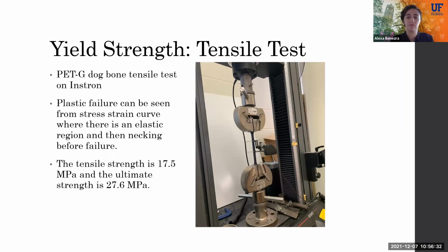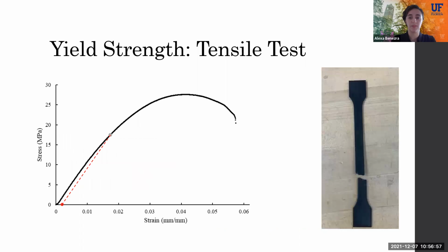A tensile test was performed on a dog bone specimen of the PETG material that's used in the housing collar, drive nut, and ejector tip. The specimen was made with 50% infill since that's what was used in the housing. When we performed the tensile test, we determined that the tensile strength was 17.5 megapascals and the ultimate tensile strength was 27.6 megapascals.